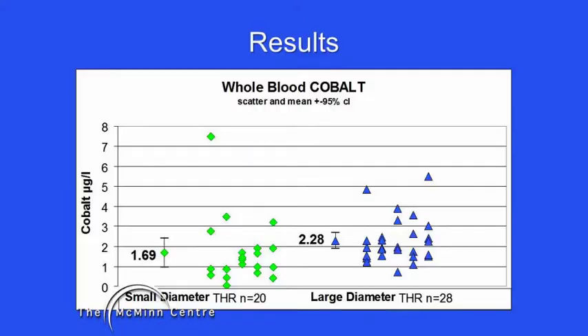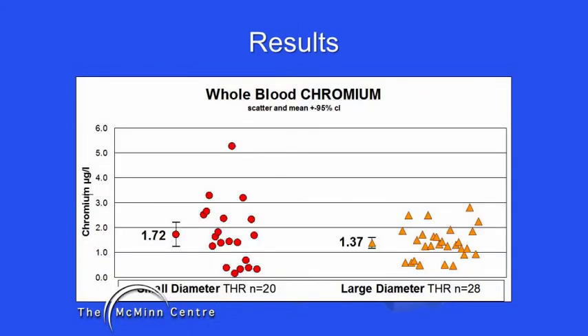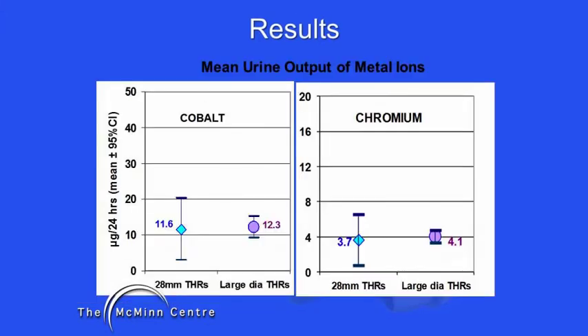The results show that the whole blood cobalt levels are within the same range. The small diameter and the large diameter means, with the 95% confidence levels, show there is no significant difference between these two groups. The whole blood chromium levels also show a similar trend, and there is no significant difference between these two groups. The mean urine output for both groups indicates that there is no significant difference between these two groups for cobalt and chromium urine output.